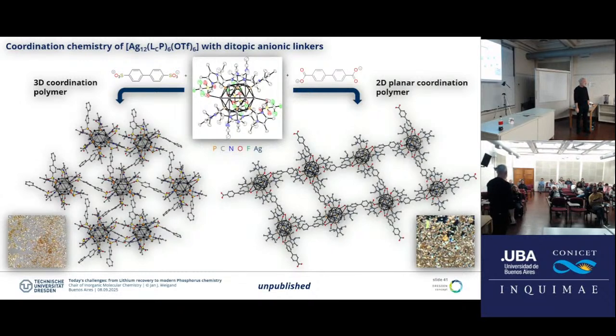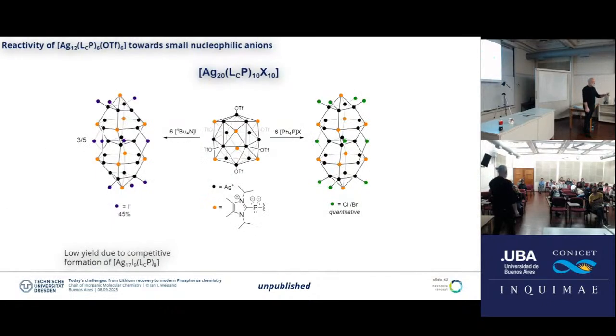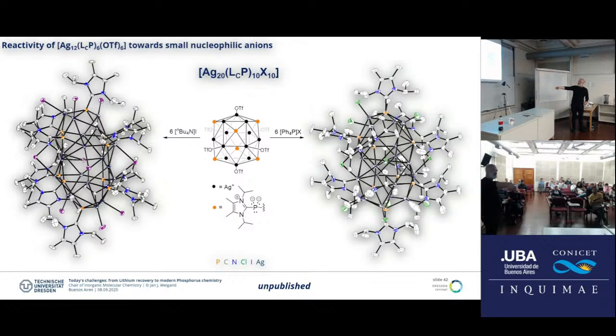for your corresponding coordination. Now I said the halogenides are for the architecture quite important. So if you take the cluster and you change over the halogenides, what we can do, we can now expand. So these clusters are in solution, they are mobile. And we can show this also by NMR in a moment. So depending on our starting cluster, if you use iodine, bromide, or chloride, we make a silver 20. And these extended clusters are quite beautiful. And they have a little bit of a difference, the iodine versus the chlorine and bromides, just by the alternating of the corresponding halogenides on your clusters.